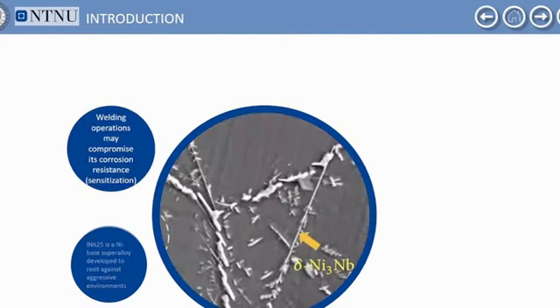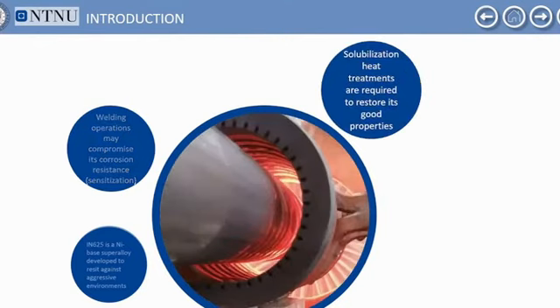The problem that we have when we have to weld these alloys is the problem that we have in general when we have to weld alloy with a very complex chemical composition. In particular, using fusion welding, we are going to destroy the optimal microstructure and induce the precipitation of secondary phases, such as delta phases in this case, that are detrimental for the corrosion properties of the welded joints. This phenomenon is called sensitization, as in stainless steel, for example. So it is mandatory to perform post-welding heat treatments in order to restore both the mechanical and corrosion properties of this alloy.